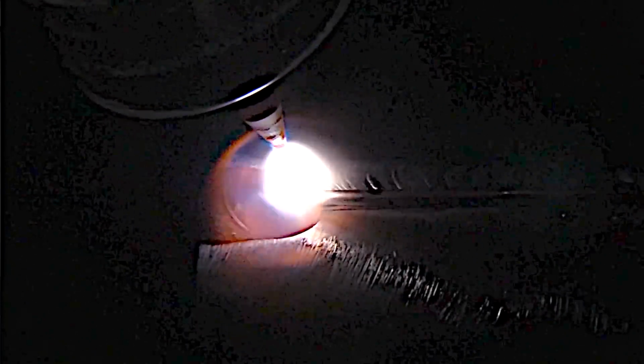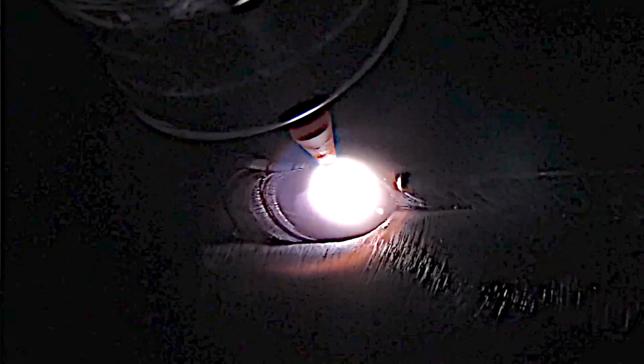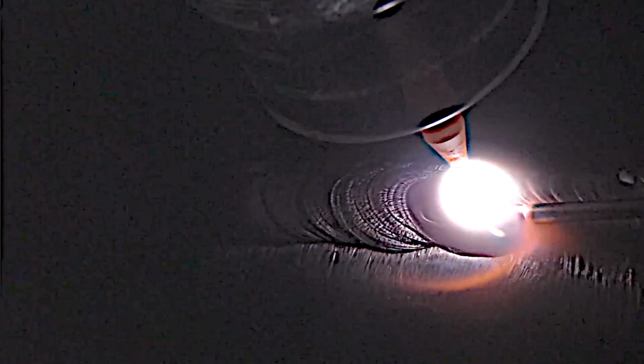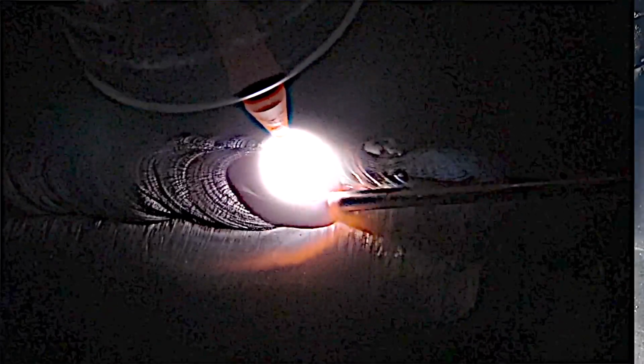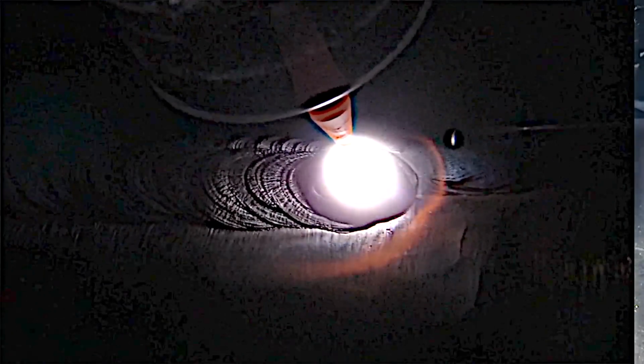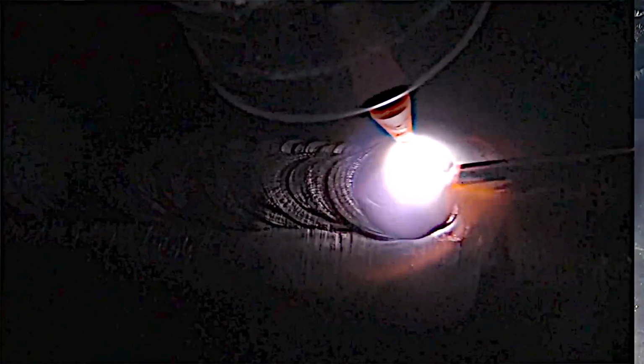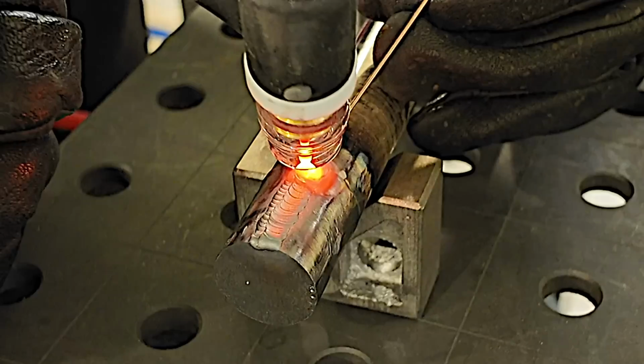And like I said, this happens to be 4140 material, so I'm using a 500 preheat, and I'm trying to keep it above 500 all while I'm welding it. And one thing that's going to happen on a job like this is that the first bead is going to go in really clean, but then as this thing gets slightly oxidized, the bead starts wandering a little bit. It gets swimming around a little bit. Not a huge deal at all, but you just got to stay the course.